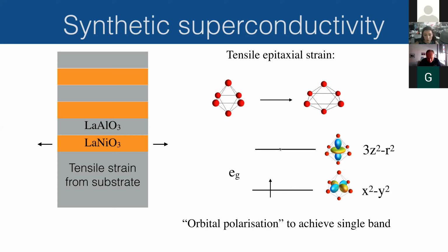Of course, you have to split this a great deal because this electron might not want to be here. It might still want to go here. And also the bands themselves are not infinitesimally thin, they have a finite thickness. So you need to do a lot of splitting. So this is called orbital polarization, meaning that you have one orbital that is fully occupied and one that is not occupied at all. So what we would like is to have 100% orbital polarization to get a single band material.